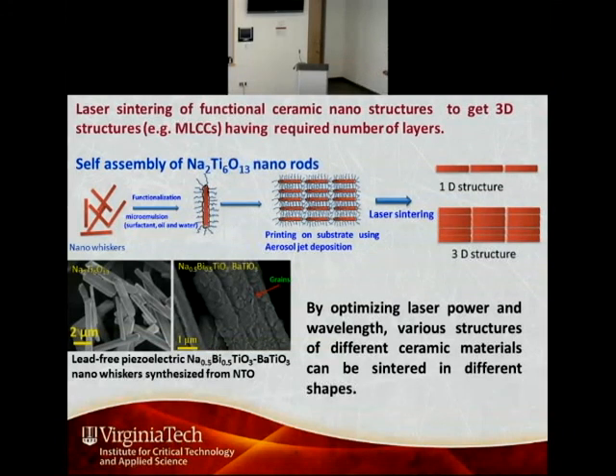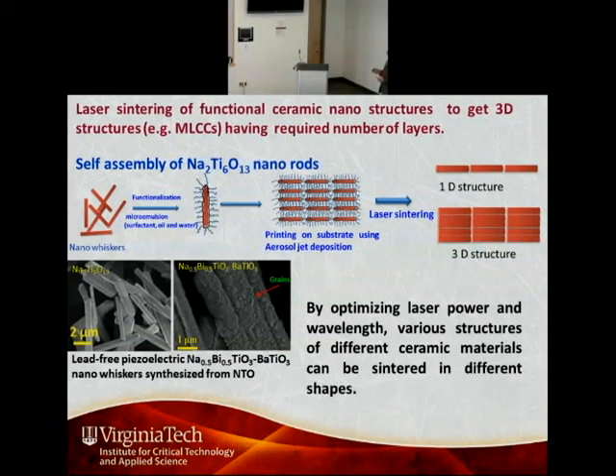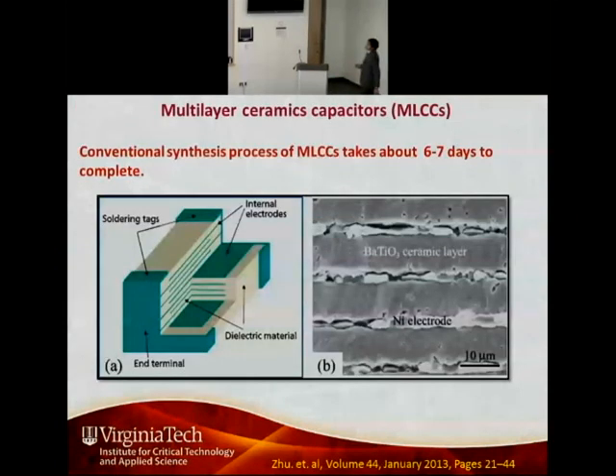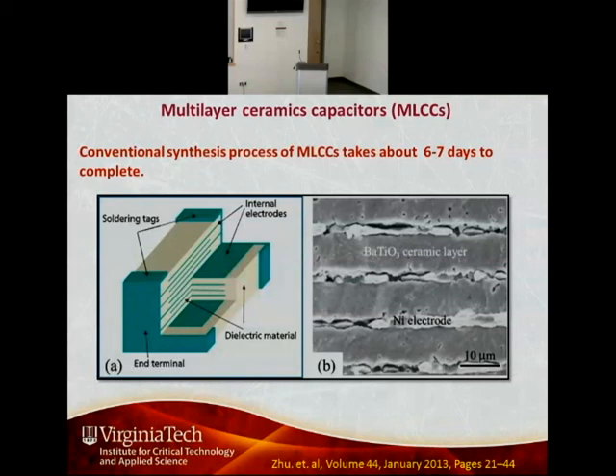The idea is that we synthesize sodium titanate rods, and then using a topochemical conversion method, we synthesize sodium bismuth titanate and barium titanate solid solution piezoelectric rods. We then mix these into an ink, and using the aerosol deposition unit, we functionalize these nanorods, and then using the deposition unit, we print them on the substrate in various structures.